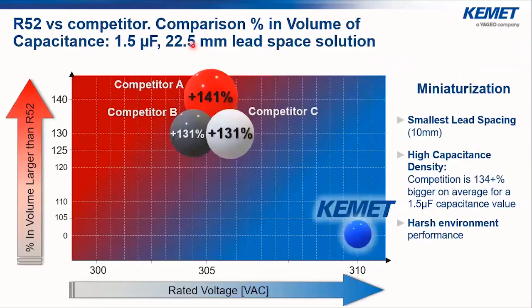So in terms of volume comparison, here is a comparison between our design of R52 of 1.5 microfarad in pitch 22.5 lead space solution compared to the same capacitance value from our competitors. So we can see, really there is a very big difference. Here is our design, and our competitors have an increased volume of plus 130, 140%, and also the rated voltage is lower. They declare 305 and we have 310 rated voltage. So really this is a series that is giving a lot of advantages in automotive and all the applications, industrial and energy, where harsh environment conditions are required, and also limitations of the space.